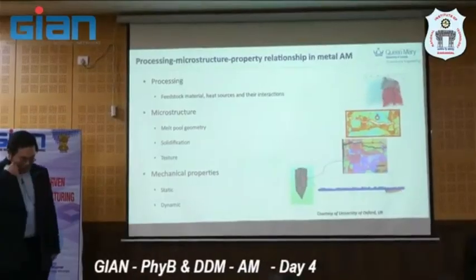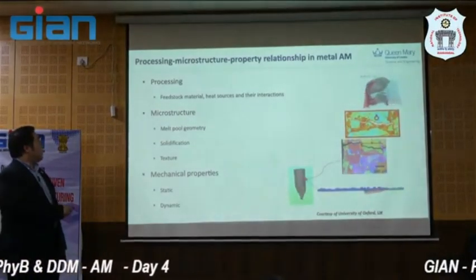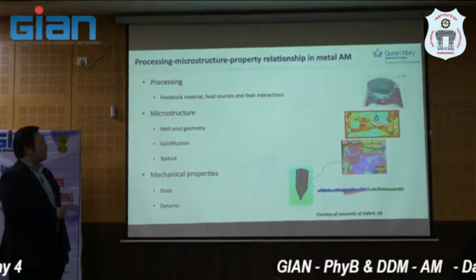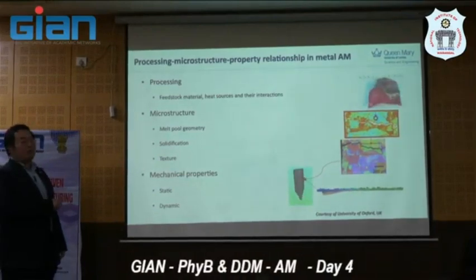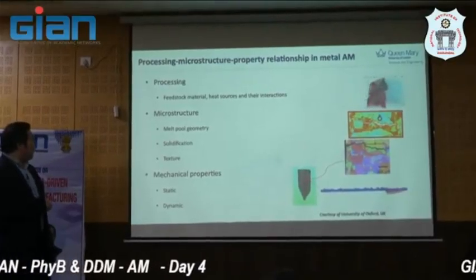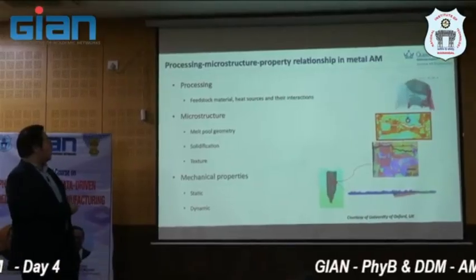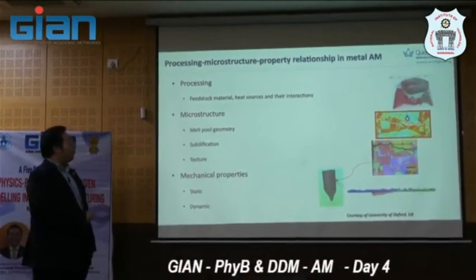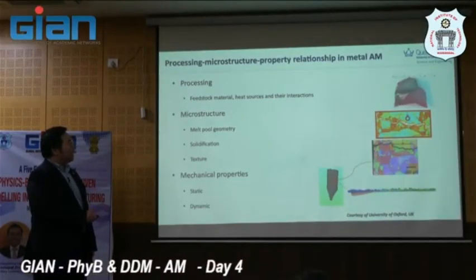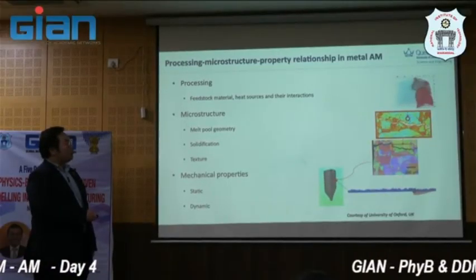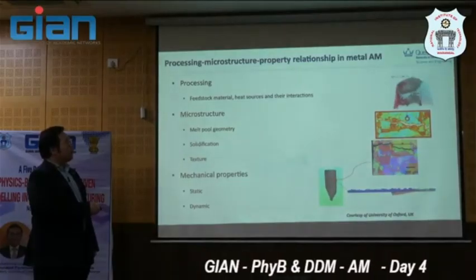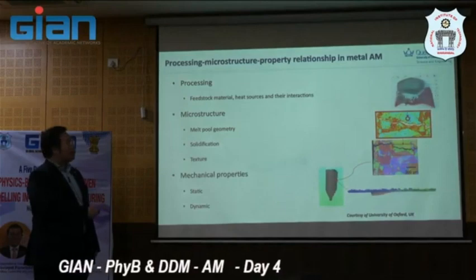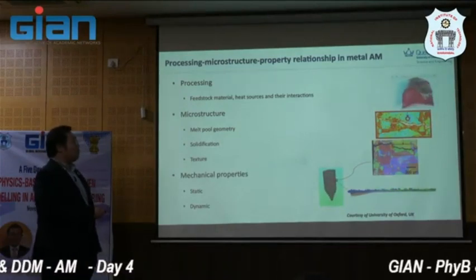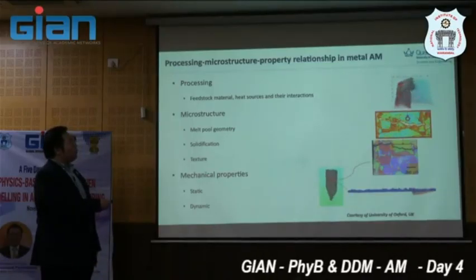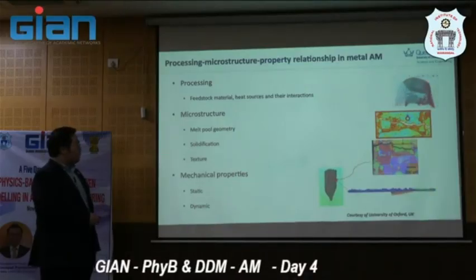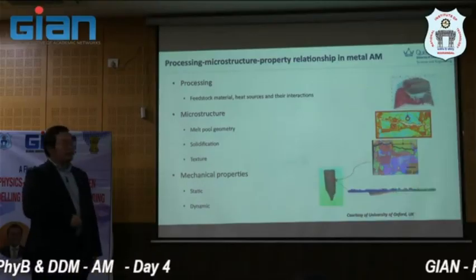As you know, this is our very first slide I presented to you at the beginning, that we now know about the processing, microstructure, and mechanical property, and defects can happen across this entire PSP, processing-structure-property pathway that we are going through. This is smaller scale. This is bigger, so this is a crack across the build, which we will talk more and more about in the slides. And then you see when we do the EBSD map here, you see the strain which is non-homogeneous anymore. And this is what we found after we did some atom probe tomography. But anyway, these are the defects we are trying to talk about today.